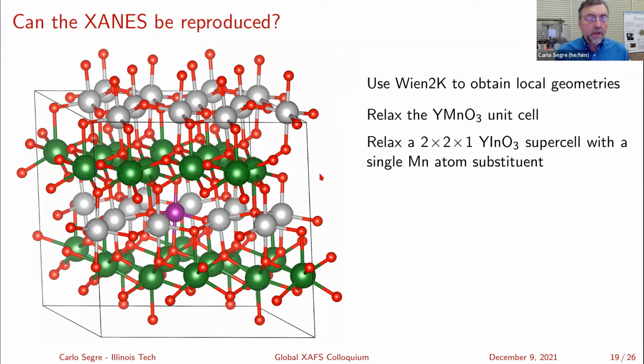The DFT calculations that had been done for the paper in 2018 were done with a random solid solution assumption of a distribution of manganese in indium, for example. And our EXAFS data said that that's probably not the right way to look at it. So what I decided to do was use this program that I happen to have, Wien2K, to try to get the local geometries and then calculate the XANES.